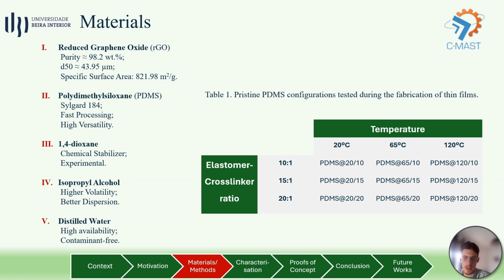Starting with the materials, the chosen filler was reduced graphene oxide, also known as rGO, which are microparticles more affordable than pure graphene that retain similar electromechanical capabilities. The chosen matrix was PDMS, a high-performance silicone very popular in this type of application, usually made up of an elastomer plus crosslinker kit. Due to the nature of the manufacturing process, various dispersants were tested, such as 1,4-dioxane and distilled water, but today we will be focusing on the one that gave us the best results, isopropyl alcohol.